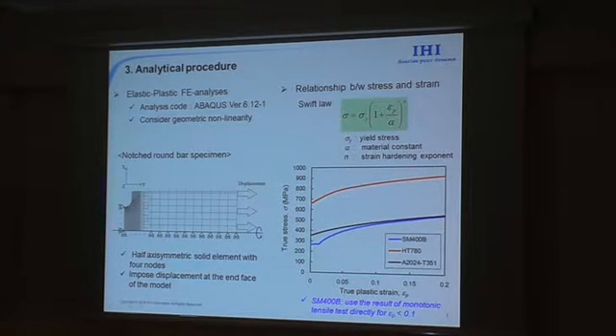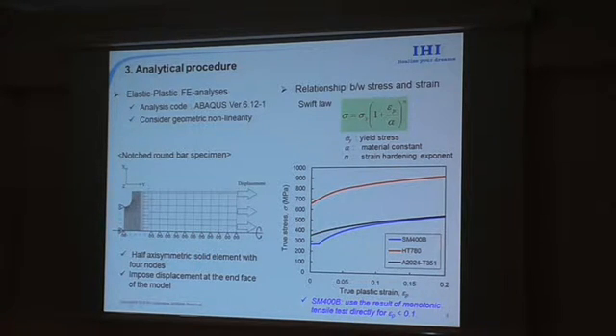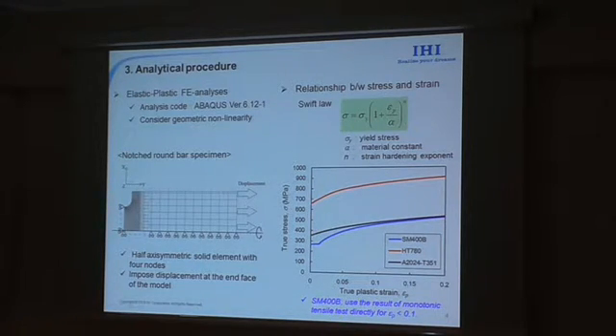I'll show you the analytical procedure used to investigate the characteristics of ductile crack initiation limit, especially to obtain triaxiality and plastic strain. Elastic-plastic FE analysis was performed using a model based on half axisymmetric solid elements. This figure shows the stress-strain relationships used for FE analysis, approximated by a power law. For SM400B, I input the test results directly within plastic strain of 0.1 in order to express the yield plateau.